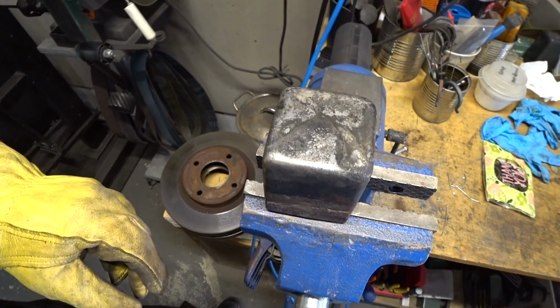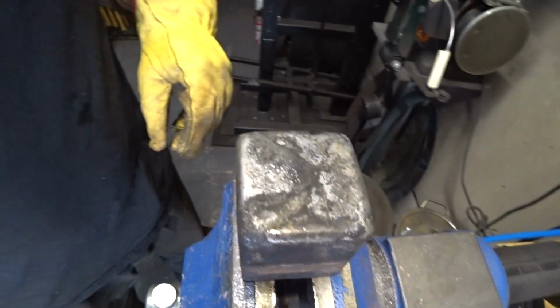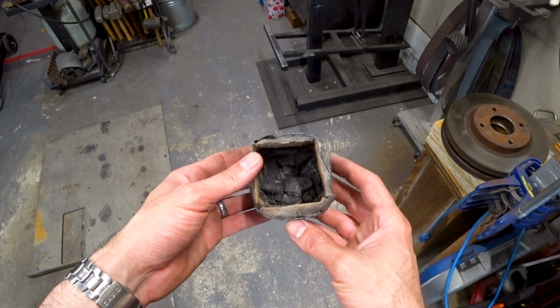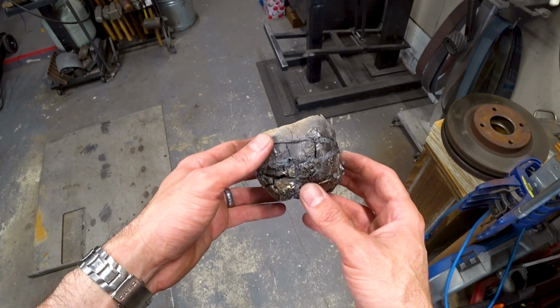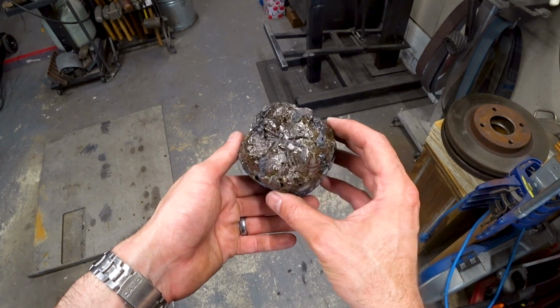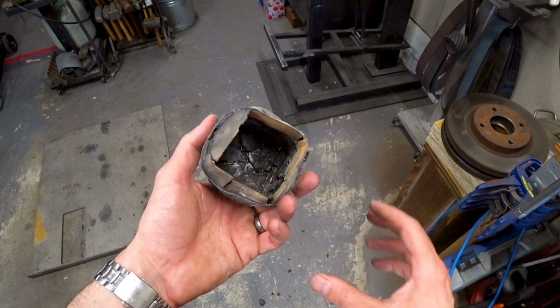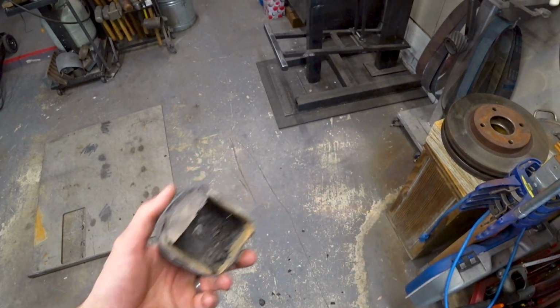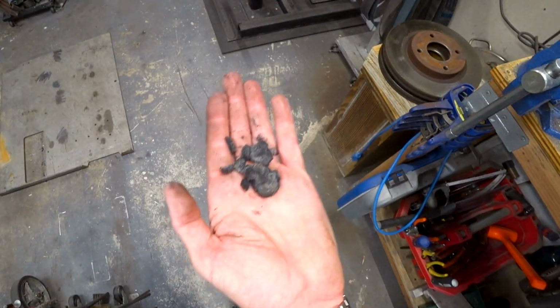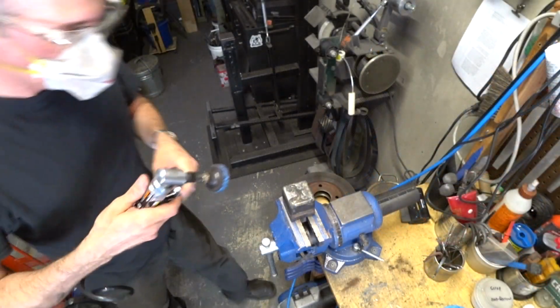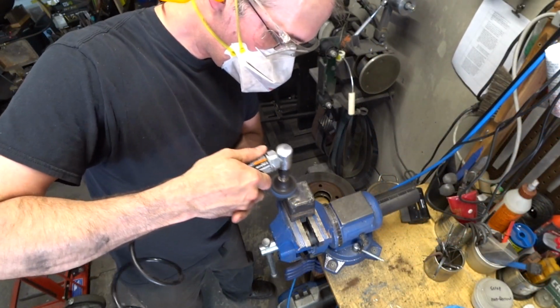And here's what it looks like after coming out of the quench. And here's what's left of the clay cap. There's still just a little bit of charcoal in there, so we know we didn't burn through it all. Here's those little bits of charcoal that fell out. Anyway, the next step is to polish the surface down to bare metal so that we can hardness test it.